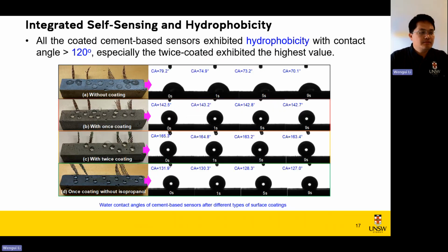Let's look at the surface water contact angle of the cement-based sensors after different coating treatment. So basically, most of the coated cement-based sensors exhibit the hydrophobic behaviors with water contact angle not less than 120 degrees. In particular, the twice coated one exhibits the highest values.